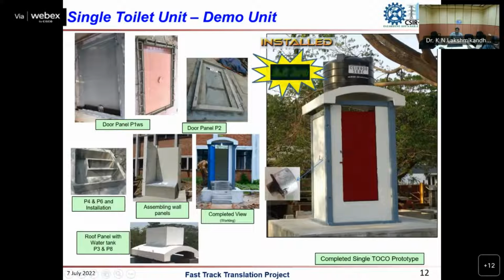We developed a dry joint system, and we trialed this in the laboratory, and we found that within 2.5 hours it is able to complete a single toilet. That means within 3 hours, we can go for usage. That is the expectation we initially aimed for.